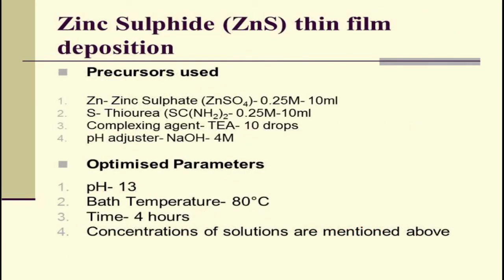Let us consider one example of preparation of a thin film, that is zinc sulfide thin film deposition. The precursors used are: for zinc, zinc sulfate 0.25 molar, 10 ml solution is taken. For sulfur, thiourea 0.25 molar, 10 ml is taken. Complexing agent TEA, 10 drops are used. pH adjuster NaOH, 4 molar concentration is used. Optimized parameters of my thin film: pH is equal to 13, bath temperature is equal to 80 degrees Celsius, time 4 hours. Concentrations of solutions are mentioned above.